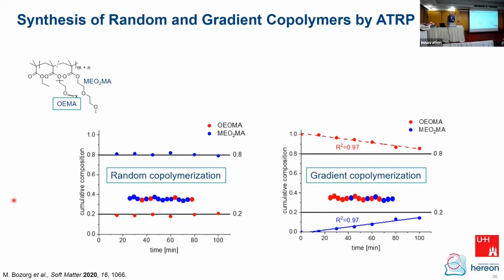But what Maria was interested in is to study the effect now of the sequence along the chain. And so she did the random copolymerization, what you see here, just put the two monomers in the quantity what you want together and polymerize. So in this case, she used 80% of this methoxy ethylene oxide methacrylate with the two ethylene oxide units and 20% of the oligo component. And independent of the time at which you take polymer from your polymerization system, you always find the same composition, meaning that you have really a pure, perfect statistical random copolymerization.